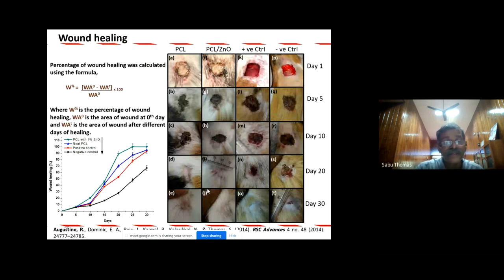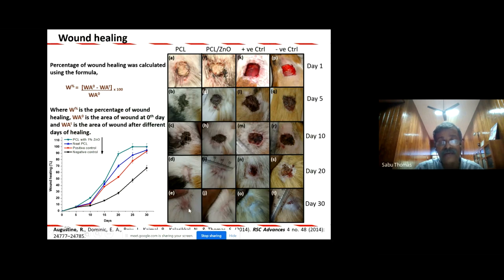And my PhD student quantified the wound healing process. You can see this is PCL, neat PCL. This is a neat PCL wound healing activity with guinea pigs. You see, you have 30 days, you have the wound healing process, but the hair growth you cannot see here. And the second one is the PCL with the zinc oxide. You see, PCL with the zinc oxide, after 30 days, you have a beautiful healing and you can see hair growth.